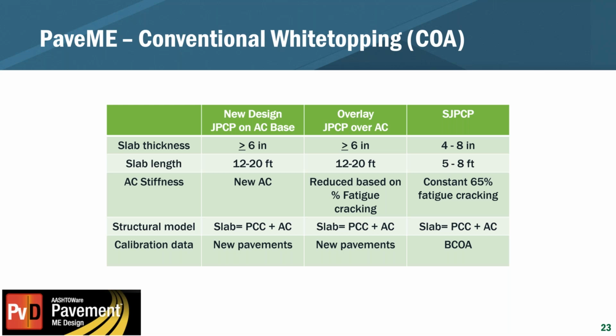So within the short joint, you're assuming a 4 to 8 inch range. That's the window, and I would even venture to say 8 inches is probably a little bit outside of the inference space based on the calibration database. But when you're looking at slab length, that's going to be a differentiating factor as well. For your short joints, that's 5 to 8 feet. For the new design, that's 12 to 20. Again, I think it will go down to 10, but you're outside your inference space. You'll get a bit of a warning too, I believe, if you enter 10 feet. So 10 to 20, and of course that 20 portion is quite long for a conventional white topping or a concrete overlay on top of asphalt.